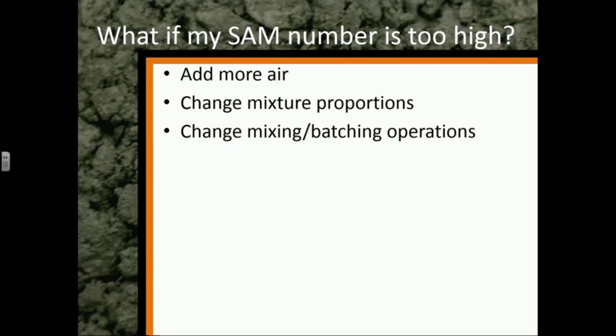If I have a truck that shows up on the job site and my SAM number is too high, about the only thing you can do is add air. As air goes up, SAM number will go down. Okay? Only thing you can do is add more air, and if you've done some trial batching beforehand, you should know about what air content you need to get a certain SAM number.